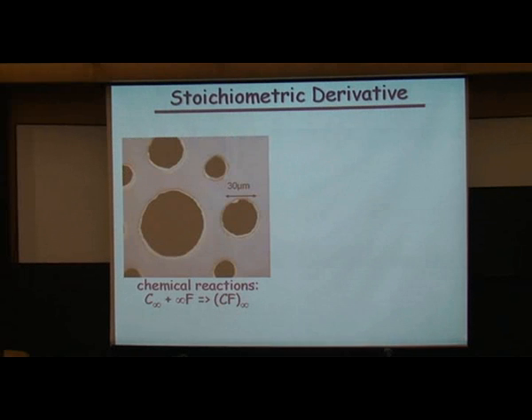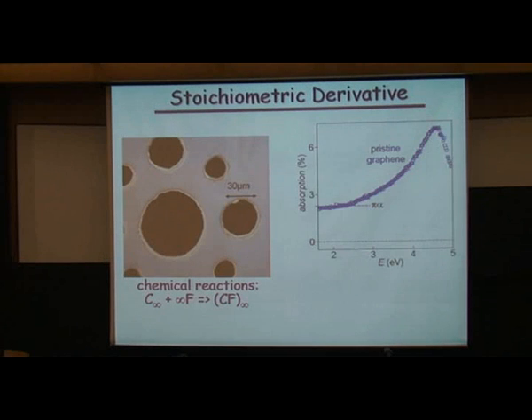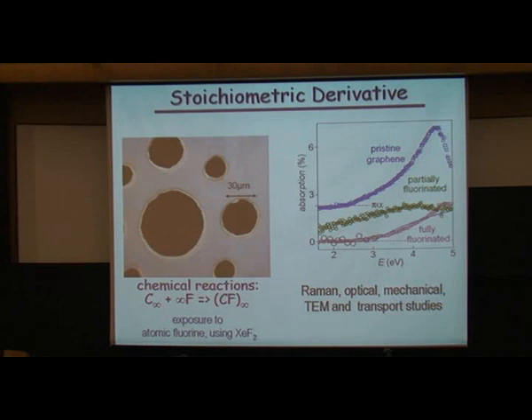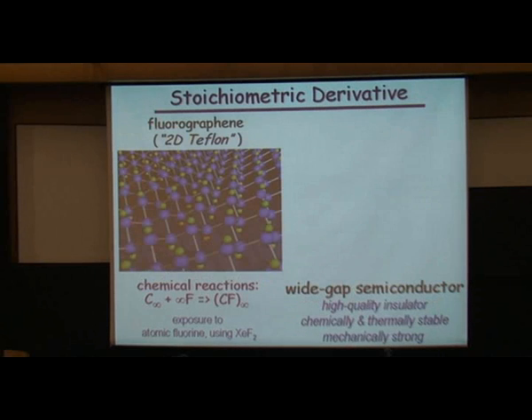So we expose graphene membranes to fluorine. This is the spectrum of normal graphene. This is the region we discussed before. Here there is some Van Hove singularity, because the spectrum in graphene becomes non-linear. You expose this to fluorine, it becomes more transparent, and when you really expose it, it becomes completely transparent, and then you can guess that there is a gap. Valence and conduction bands start to absorb light at something like 3 eV. We spent a lot of time on this, but I have no time to describe this one.